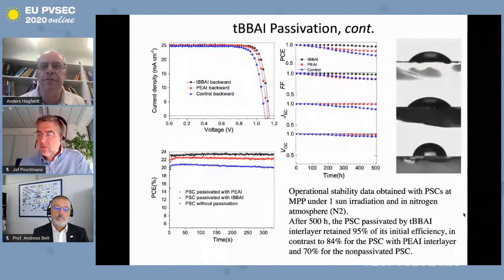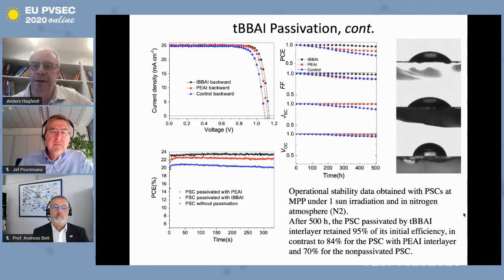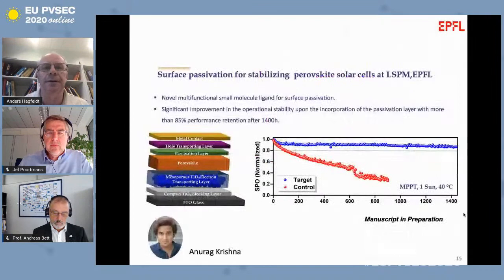And one can see the hydrophobic result if we do contact angle measurement, as you see to the right with a drop of water. And you also see good efficiencies, 24%, and also very good stability over 500 hours under operation at maximum power point. So it does show that the passivation decreases the non-radiative centers, but also improves stability.